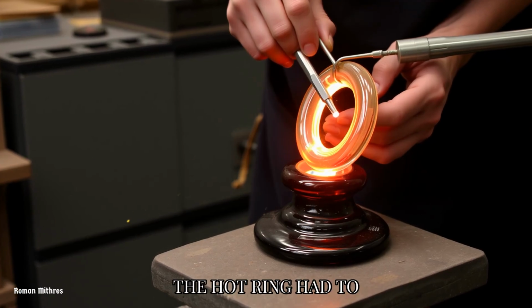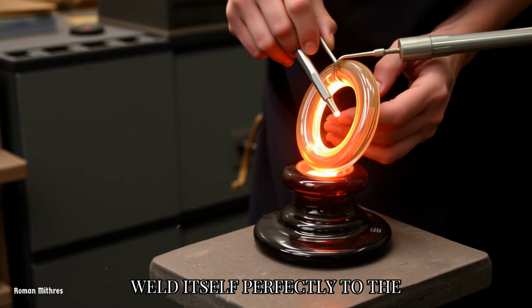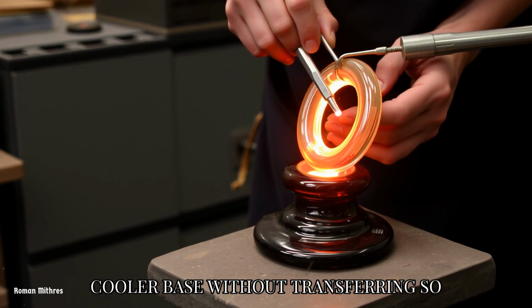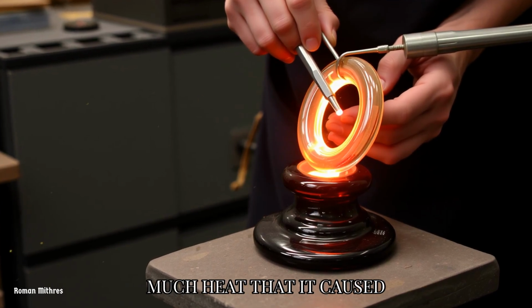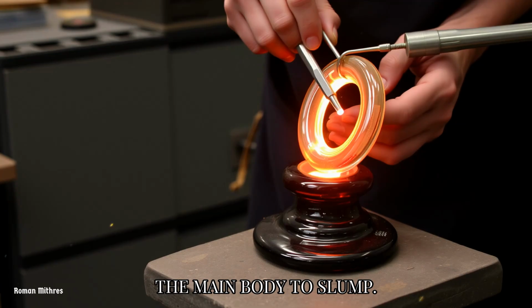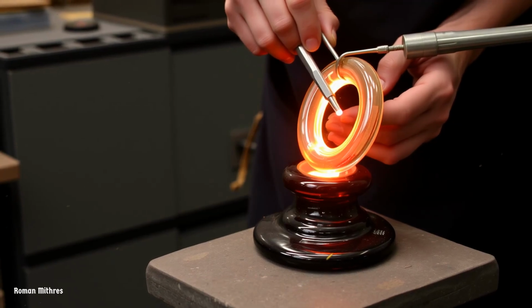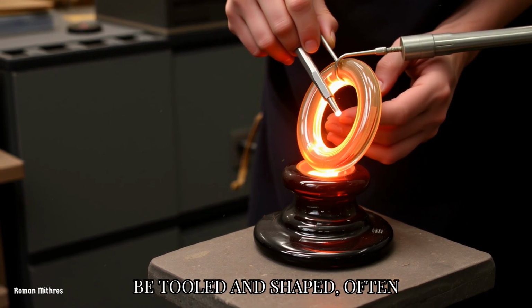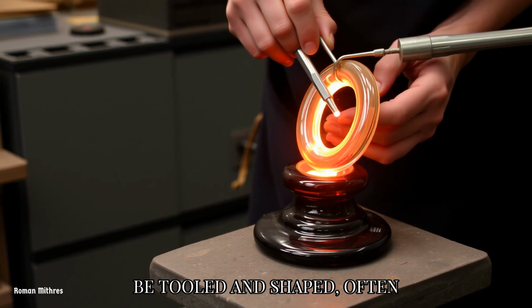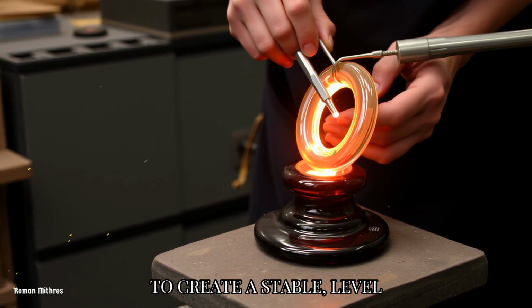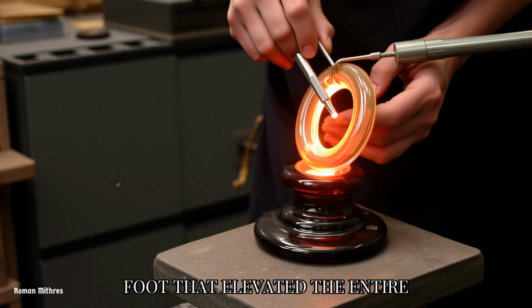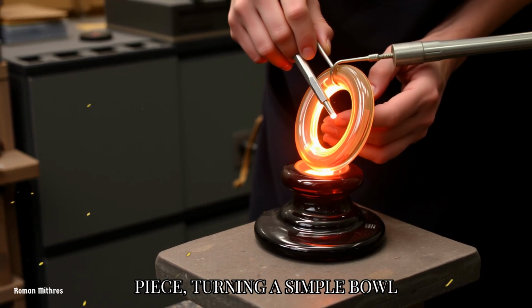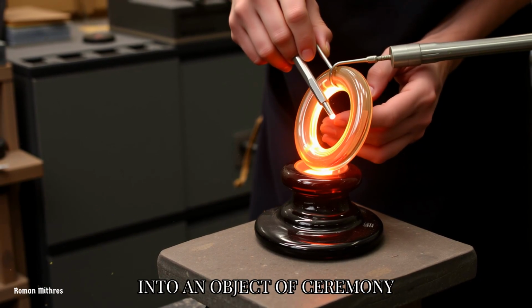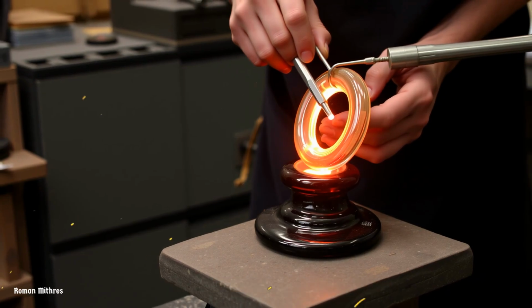The hot ring had to be just fluid enough to weld itself perfectly to the cooler base without transferring so much heat that it caused the main body to slump. Once attached, the ring could be tooled and shaped, often pressed flat on the marver to create a stable, level foot that elevated the entire piece, turning a simple bowl into an object of ceremony and status.